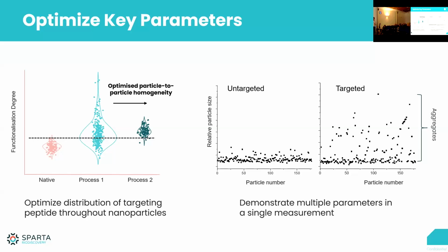But the nice thing with SPARTA is that we can see that at the same time, but also look at some of these aggregates and investigate their spectrum and see, okay, did they just aggregate but have a relatively small amount of targeting ligand, or are these also the particles that have maybe 3 or 4 times as much targeting ligand? So we can really investigate why these particles are aggregating.